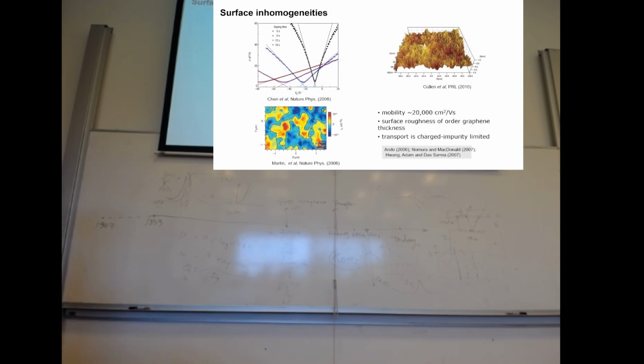At that time, people did a lot of investigations using STM and other techniques. For example, this is just evaporating some dopants on top of graphene. At the same time, there's a shift of the Dirac peak. That means your Fermi level is moving, and also the slope of conductivity is decreasing. That means the mobility is degrading also. There are also some STM studies showing a lot of inhomogeneities on the microscopic scale. For example, this is the electron-hole puddles, a very famous picture, where even at the Dirac point you have fluctuations of electrons and holes. That gives another story behind it: there's a minimum conductivity, which has been puzzling people for years.